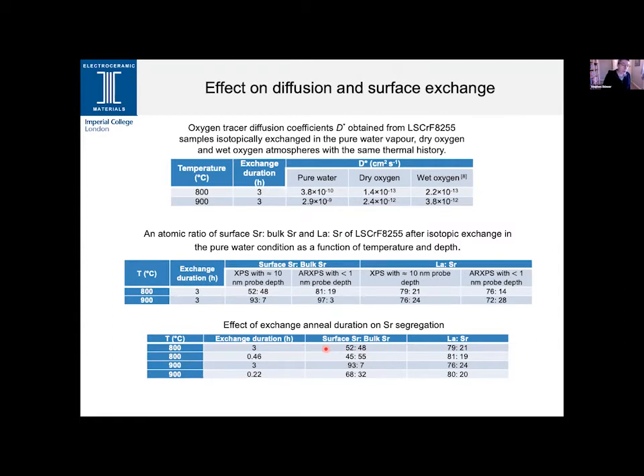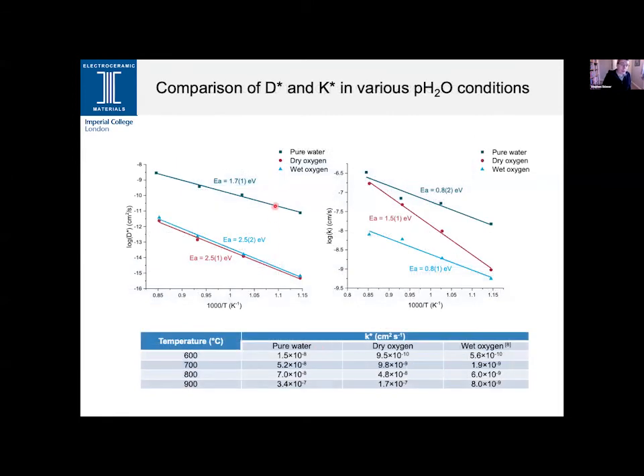To illustrate that over the full range of temperatures that we've analyzed, we have the three sets of data here: the wet oxygen, the dry oxygen, and that pure water atmosphere. The activation energies for both wet and dry oxygen are very similar. Overall diffusion parameters are within error. The pure water, that reducing condition, has a slightly lower activation energy and that significant increase in the diffusion kinetics. Turning to the surface exchange parameter, on the other hand, the wet oxygen suppresses that surface exchange reaction in comparison to the dry oxygen environment, but the activation energies are dramatically different. Whereas in the pure water environment, the surface exchange is apparently significantly improved. And that's illustrated in the determined parameters in the table here.